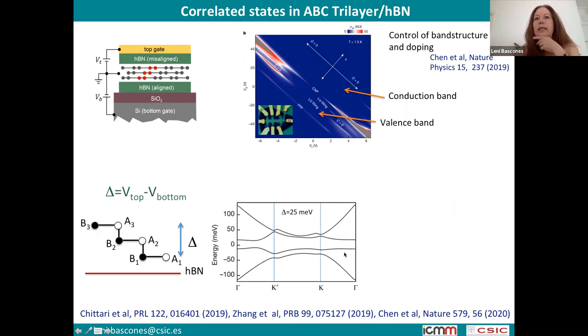So the flat band that we have isolated here is the valence band, and it's where one observes these effects. You see these changes are associated to the emergence of insulating states. In fact, you can see that moving in this direction, what we observe on the positive side is quite different from the negative side.